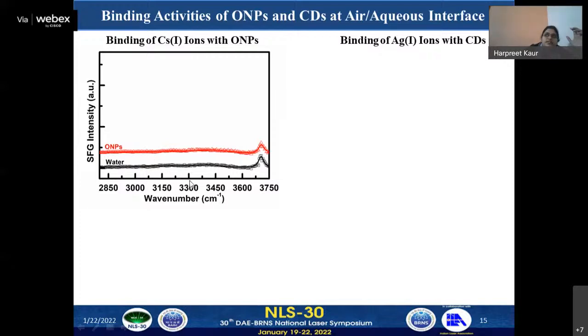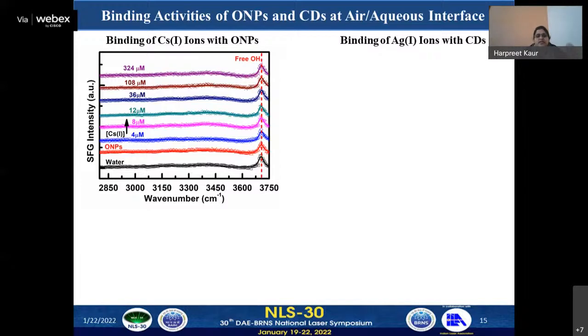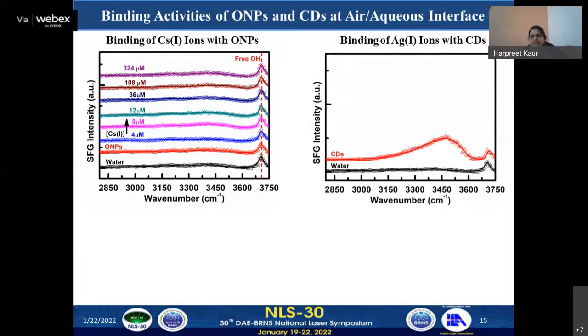This confirmed that the organic nanoparticles have no impact on the interfacial water structure, or it means organic nanoparticles prefer to stay in bulk or have a disordered conformation. With further increase in concentration of cesium ion in the organic nanoparticle solution, we have not observed any significant change. But in case of carbon dots, we have found that there is an overall enhancement in the SFG intensity in the OH stretching region, which confirms the hydrophobic ordering of the interfacial water molecules.